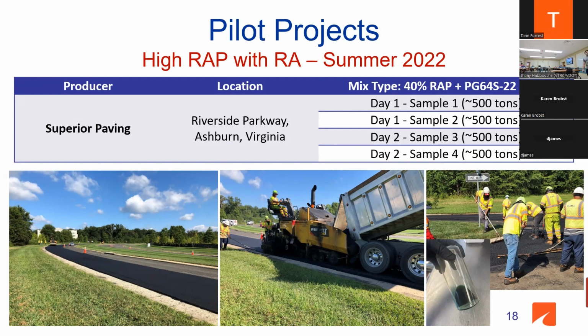That mix had a high RAP content, but also the chemical component, the recycling agent, which you see as the product in green, added just to make sure it addresses the stiffness. The more recycled material, that's RAP, aged, stiff material. It loosens it a little bit, softens it a little bit, makes it perform better, and workability-wise and compactability-wise, it's better as well.